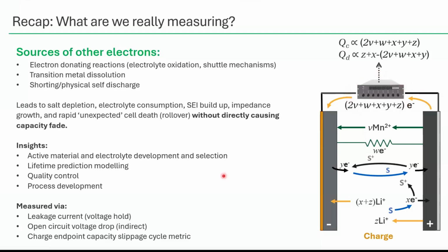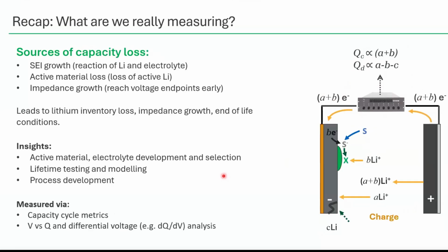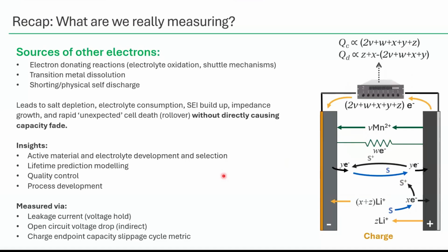So if we can capture the electrons we're losing due to capacity fade mechanisms, and then all these additional things, which in traditional cycling equipment, I'll show later, is actually kind of invisible mechanisms, because the rate at which these happen are so small, we can get really interesting mechanistic insights into active material, electrolyte development selection, lifetime prediction modeling.